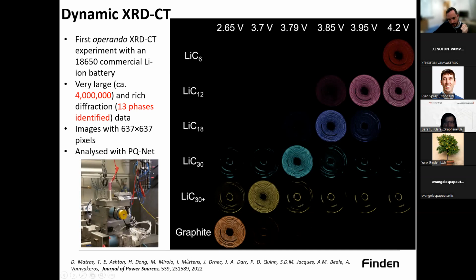We were able to see here part of this experiment was this charging process. So we went from 2.65 volt, nothing really extreme here, to 4.2, and we tracked the evolving solid state chemistry. We're able to see that apart from the main part of the cell, let's say, that is homogeneously being lithiated, there are other regions that have a different degree of lithiation. There are parts that are inactive, but there are also parts that are just slower in lithiating, that are active though.